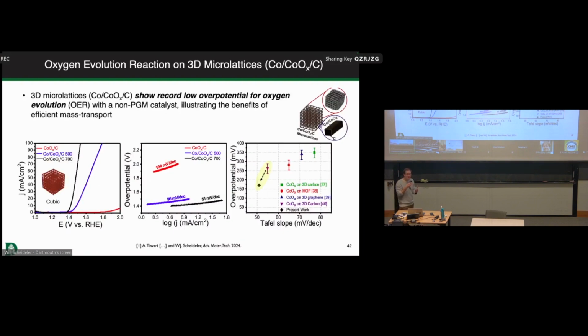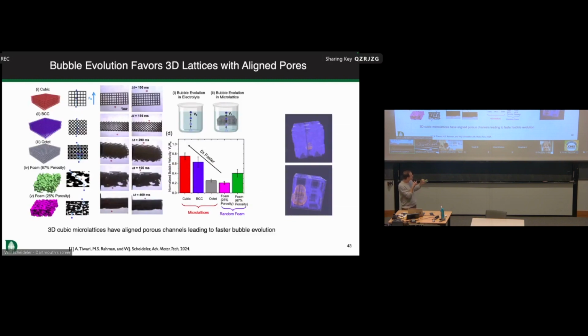The cobalt oxide are perhaps the most high-performing materials that we've developed by this approach. And if you benchmark it against the commercial standard, for these metal oxides it is typically a metal foam. Well, that metal foam is a random porous architecture. This is an ordered porous architecture, so we have control now of what the bubble evolution will look like. So Cypher developed a really nice experiment for this.